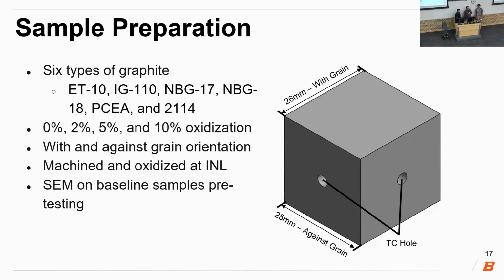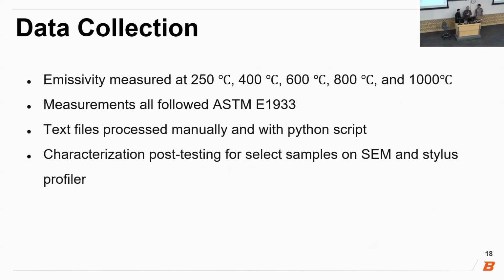So we were testing 6 types of graphite, 0 to 10% oxidation, with and against grain orientation. All samples were prepared at the INL, and SEM images were taken on 0% oxidation samples. Each sample was run from 250 to 1,000 degrees Celsius, and measurements all followed ASTM E1933. Some characterization was also done on select samples after we were done.